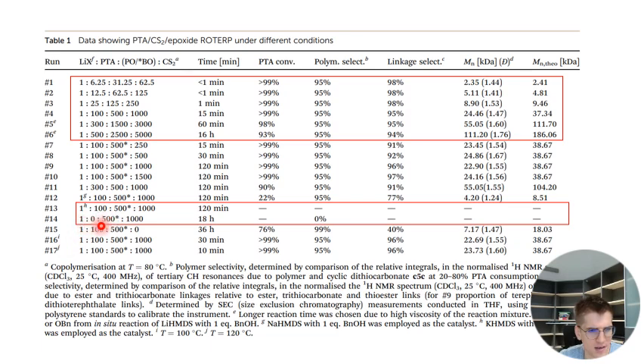When you had no PTA and you did it at 80 degrees, that was the temperature that I conducted the polymerizations at. It was a bit trial and error, which temperature I took. Lower temperatures worked, but they were relatively slow. And for higher temperatures, because CS2 and PO are so low boiling, I was always a bit worried that my reaction vessel would leak. 80 degrees is already over the boiling point of CS2 and PO. But it remained stable, but at much higher temperatures, sometimes it leaked, just due to the pressure that was building up. So that's why I stick with 80 degrees. And at 80 degrees, if you don't have any cyclic anhydride, thioanhydride present, yeah, you do not form any polymer. You just form the cyclic dithiocarbonate, no polymer, which means that the terpolymerisation really did improve the polymer selectivity of the process a bit.